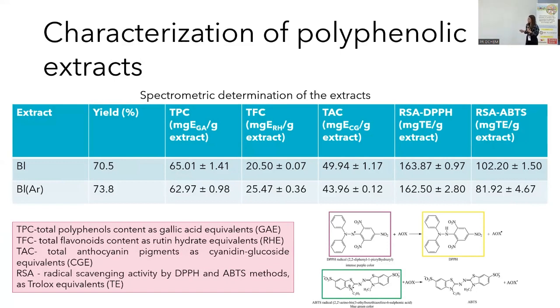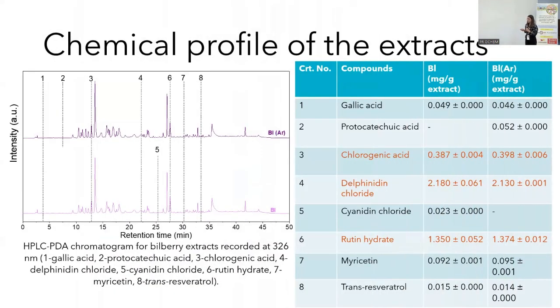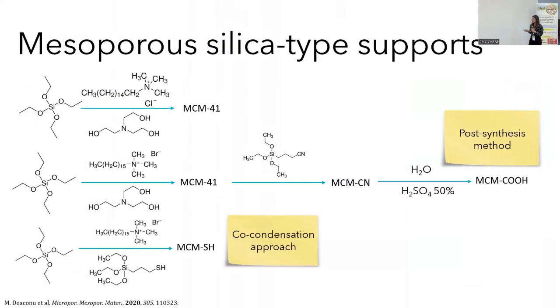The highest contents of anthocyanins were assigned for the conventional bilberry extract, whereas the highest contents of flavonoids were discovered to be for the inert atmosphere extract. The radical scavenging activity was best assigned with DPPH assays for both extracts. Up to 8 different compounds were identified in the extracts, the most abundant being delphinidin chloride, rutin hydrate, and chlorogenic acid. We proposed 4 different mesoporous matrices to encapsulate the extracts, the first one being pristine MCM-41 silica,